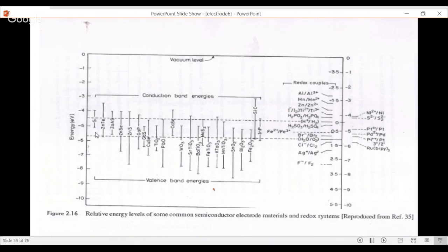The valence band potential is not more positive with respect to oxygen evolution. So silicon cannot promote the oxygen evolution reaction, only the hydrogen evolution reaction. That is why silicon, even though a semiconductor, is not considered for water decomposition reaction, because it cannot decompose. Even titanium dioxide is the same case, pure titanium dioxide. It cannot evolve hydrogen, but it can evolve oxygen.